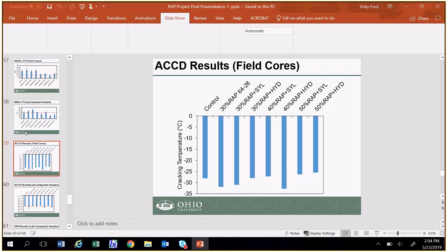So that slide, is that design acceptance or design? This is for the design. Specifically, when you talk about performance, are we talking about years here, or testing performance, like the actual physical data? The recommended is based on the mix design, where we would like to do a long-term aging. For quality control it's different; we did not really recommend SCB, we recommended just the ITS, basically to make sure the mixture is holding up. But for the mix design, we recommended using the SCB, based on the long-term aging.